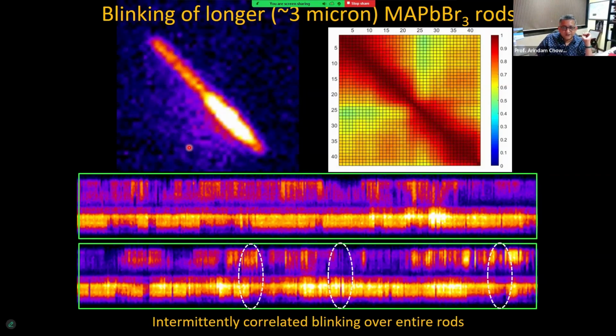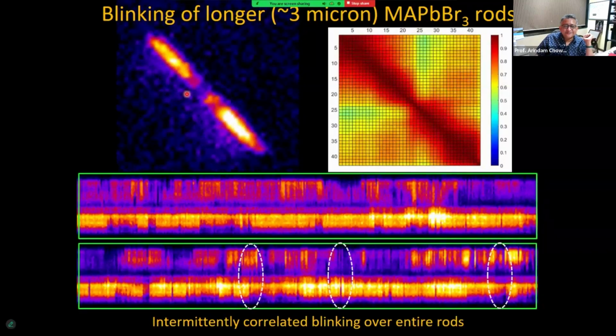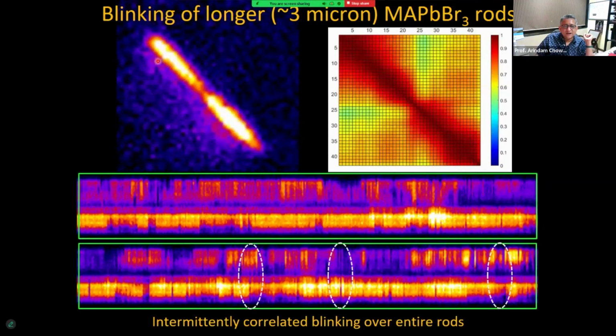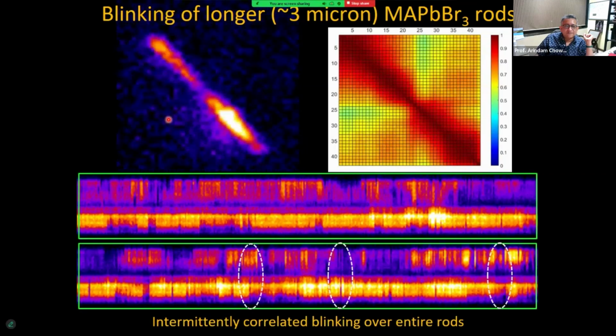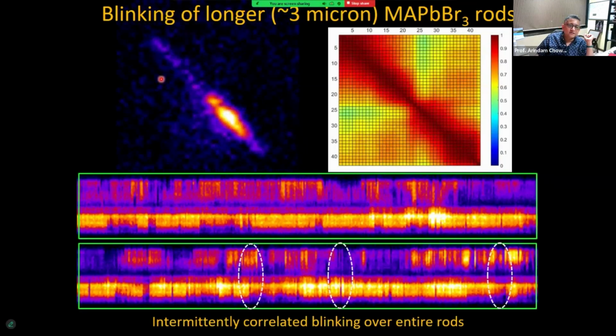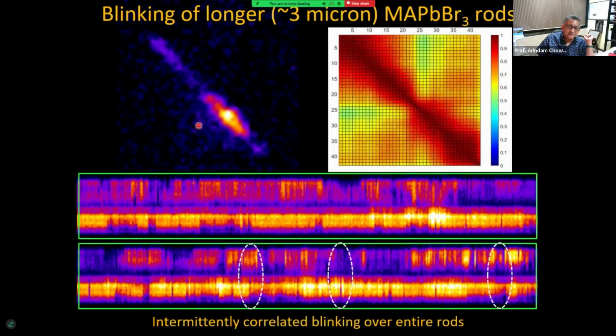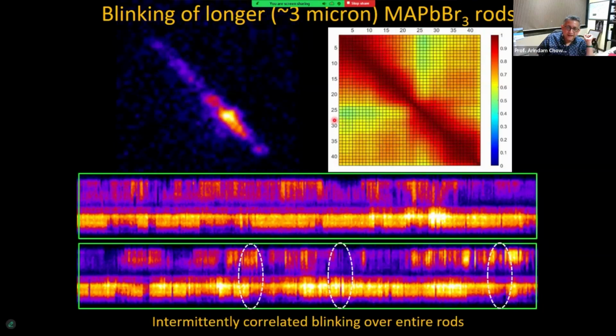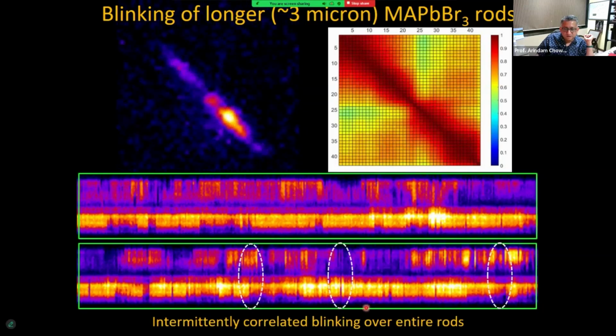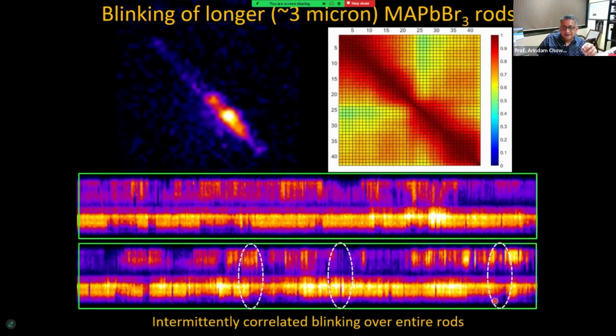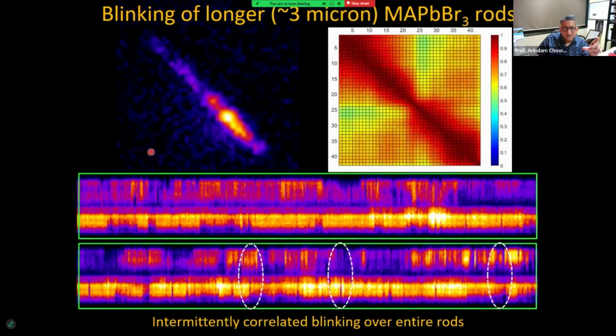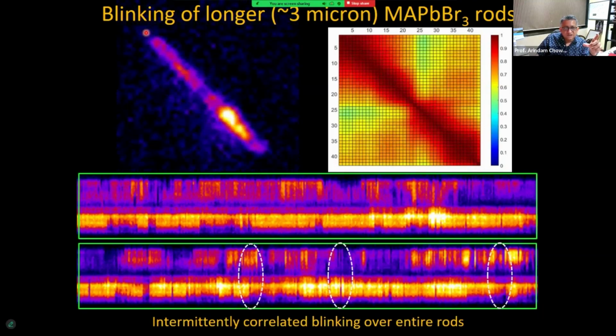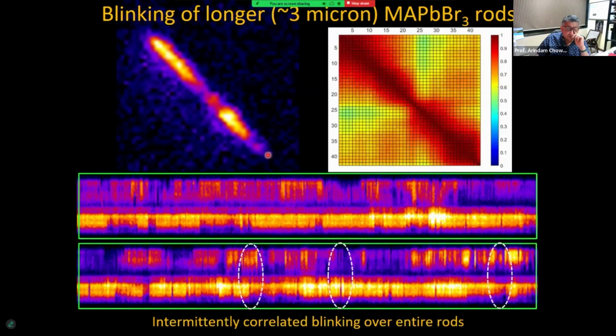So I'm kind of showing the same thing again here. But if you look carefully in this entire rod, you will see one segment on the top left, which is undergoing a correlated blinking behavior. And then there's this bottom left segment that is also undergoing a correlated blinking behavior, as you can see from the correlation matrix. However, if you look carefully, there are events where the entire rod, which spans from about here to about here, almost the entire part of this movie that I'm showing you here.